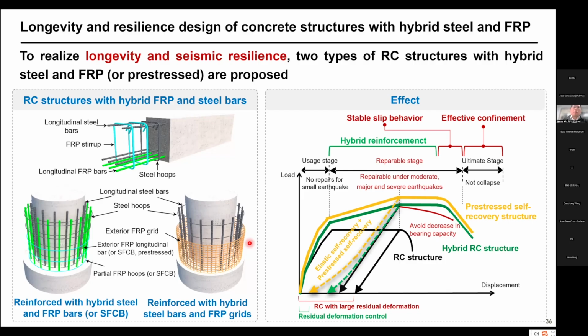And also, by using the linear behavior of FRP together with the bilinear behavior of the steel bars, we can achieve this kind of structural behavior. So it will have a secondary stiffness under a large earthquake effect, and very good recoverability after the earthquake. So it not only can enhance the durability, but also the structure's toughness.